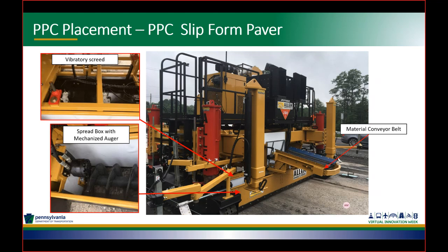The whole machine is mounted on tracks. There's a conveyor belt in the middle of the machine moving forward. The mixed volumetric trucks dump polyester polymer concrete, already mixed, on this conveyor belt. The polyester polymer concrete falls in a spread box and is distributed by an auger and vibrated by several vibrators. So very high production. I took these pictures on a large project in District 6.